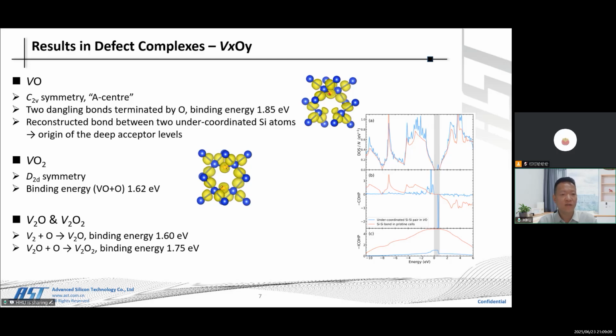VO2 has D2d symmetry, with a binding energy of 1.62 eV. There are also complexes V2O and V2O2. For V2O, the binding energy is 1.6 eV, and for V2O2, the binding energy is 1.75 eV, as shown on the page.